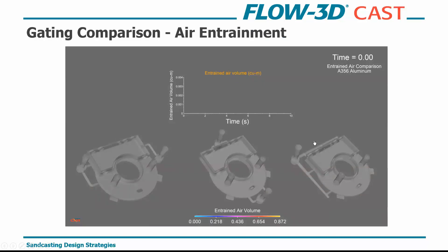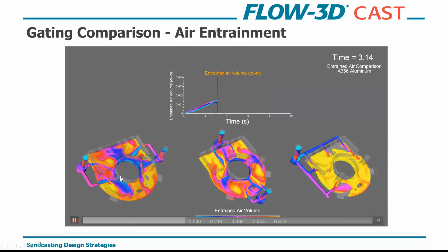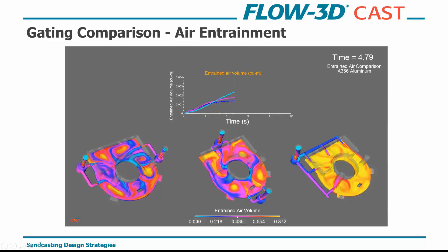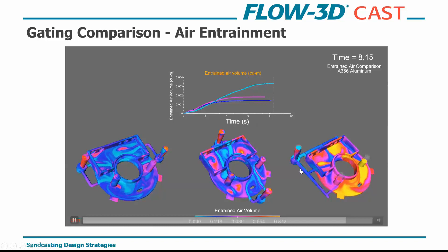Now we fill the parts. We're happy with risers and their placement, and we want to look at differences in air entrainment across three different design iterations: our initial design, a design with the rig rotated 90 degrees, and a single sprue with double risers gating into the system. We're outputting entrained air volume. The initial design with two opposed filling points will cause converging metal fronts and add turbulence. The single sprue has quite a bit of entrained air. Our initial design is still behaving the best.